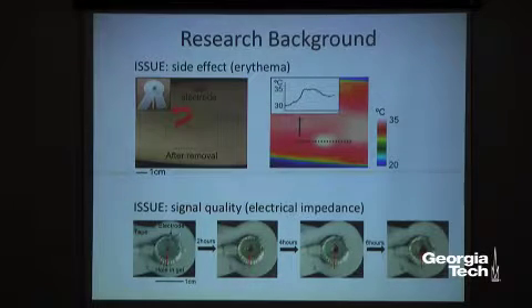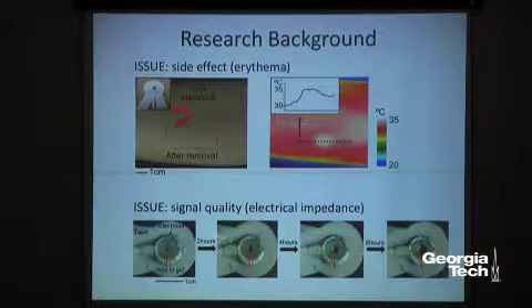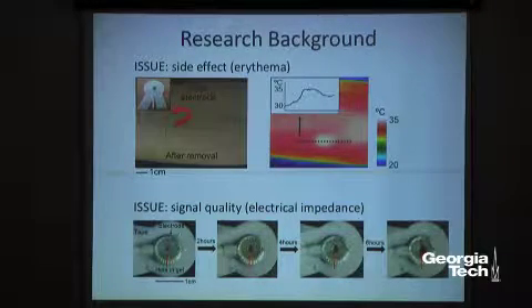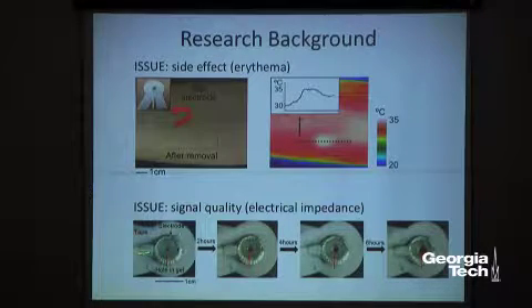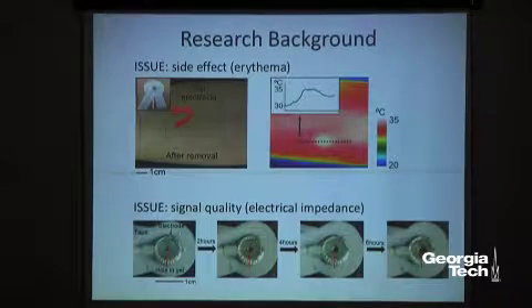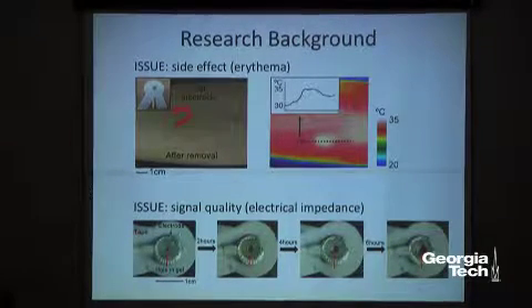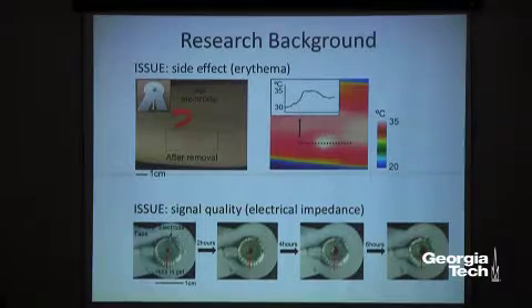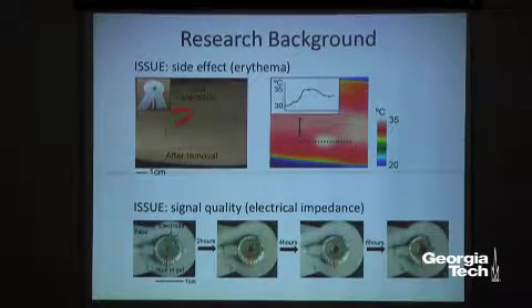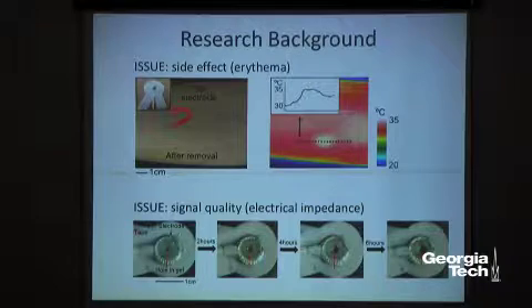But on the other hand, the bigger issue is here. Now, in terms of signal quality, that's what you want. You want to have a nice high fidelity electrical signal of electrocardiogram. But now, since this electrolyte gel is evaporating over time, right? So now you have this gap. Then the problem is your electrical impedance is increasing, so your baseline noise is also increasing, so you're losing the quality of your electrocardiogram signal. So that's really bad in terms of signal recording. And now we have to address those issues, right? We need to remove the gel. We need to make it